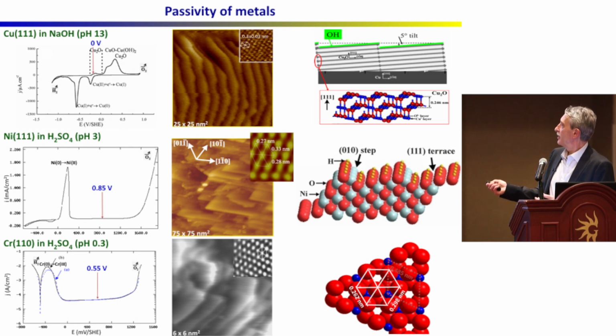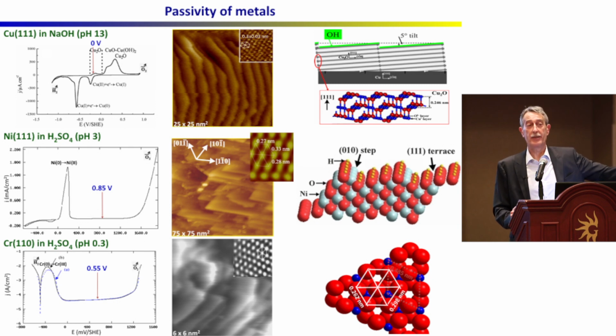and you can also see these very clear features that are characteristic of a crystalline material, although the thickness of these layers is of the order of 1 to 2 nanometers according to XPS, or also according to just reduction of the oxide that you can do at the end of the experiment and just measure the charge. So we know the thickness from the electrochemical measurement and from the XPS.